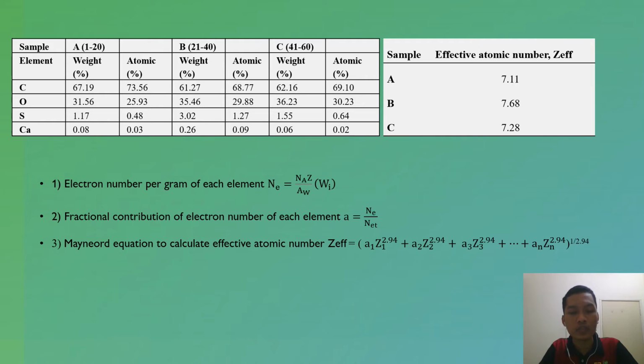It is also worth observing here that the sulfur and calcium content is mostly abundant in the B group, but then it starts to decrease from the age of C group. This can be explained that as we grow older, the amount of minerals in our body decreases as we lose appetite and also because of the deficiency of kidneys to retain these minerals in our body as we grow older.